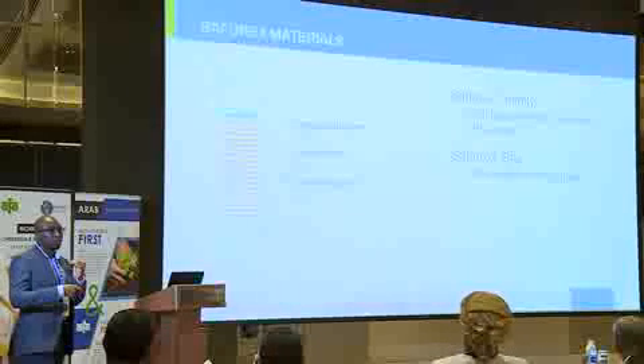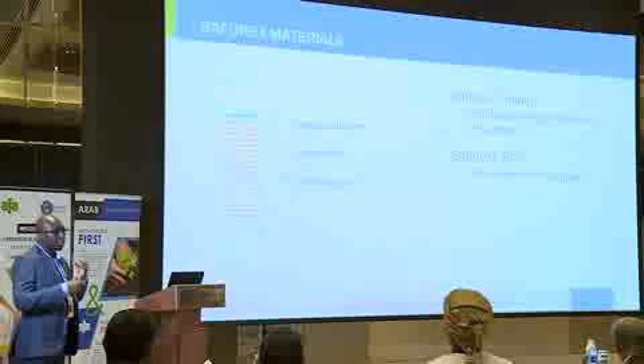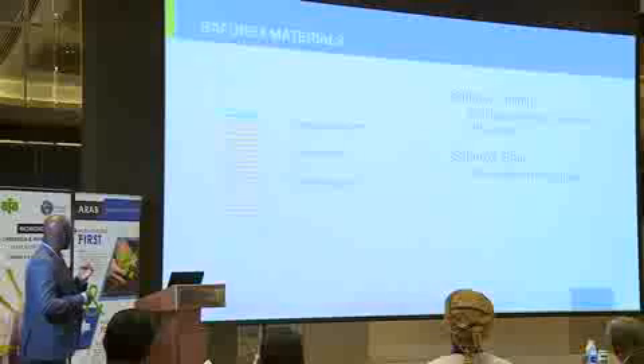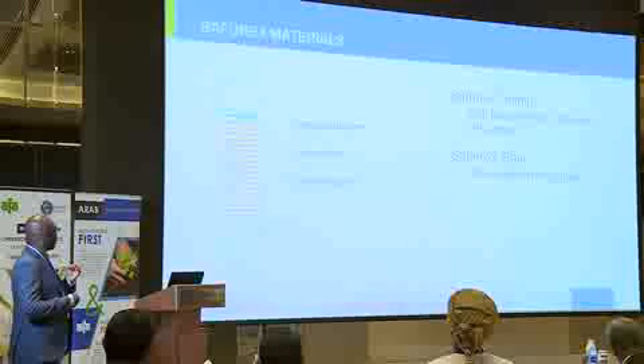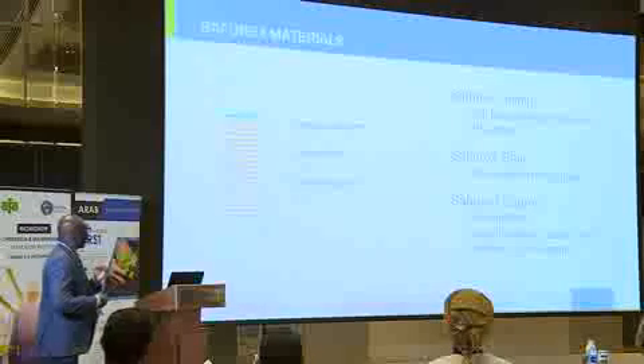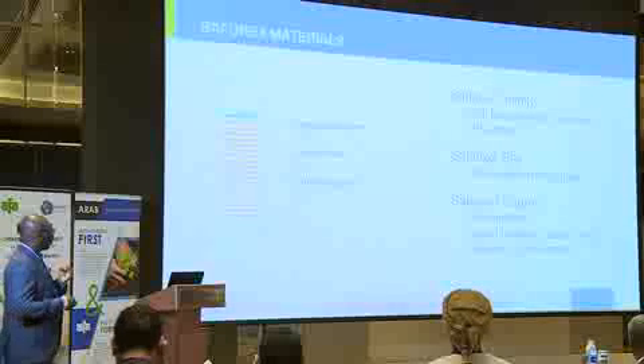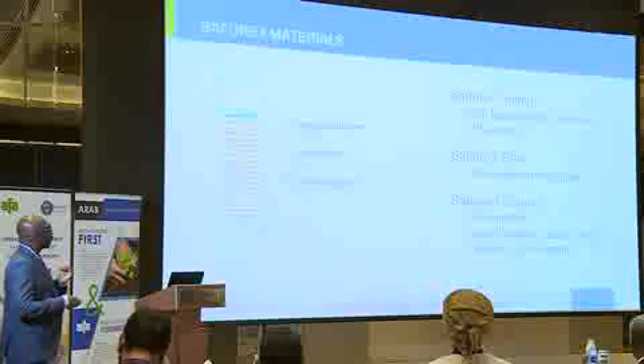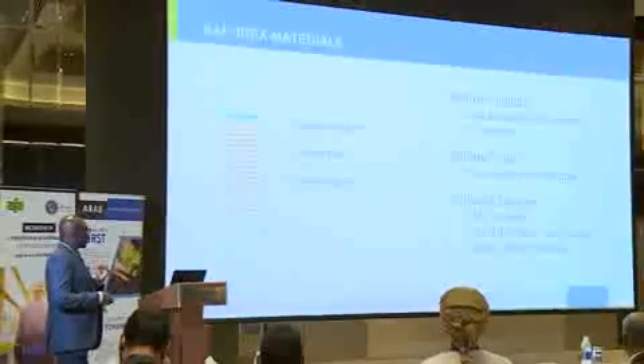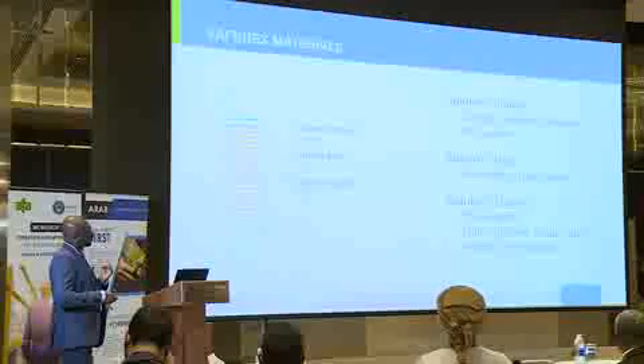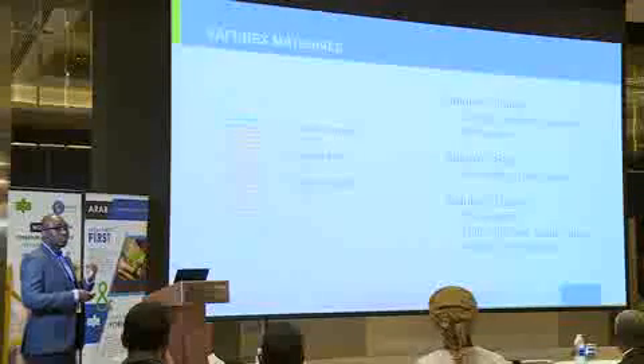The tubes, which are in orange, will then be Safurex Star because that is the material specifically developed for the process conditions in the HP stripper tubes because temperatures here are much higher than here. And then for the liquid dividers, which are in blue, you would have Safurex Degree, which is the same as Safurex Infinity, but just that this is produced from powder metallurgy. And for Safurex Degree, you can have liquid dividers, radar cones, and then large forgings made from this.